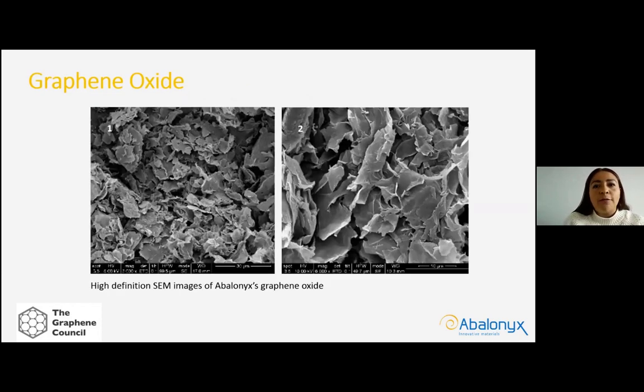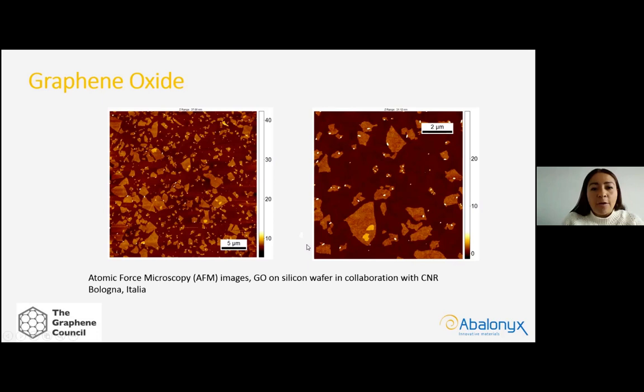So graphene oxide. Here I am showing you some SEM images of graphene oxide. These images are taken in bulk materials, so you cannot see here single sheets of graphene oxide, but you can see already the sharp edges of this material. And here is the AFM image of GO taken on silicon wafer, where you can see a single layer of graphene oxide. The average thickness of this material is 1 nanometer, and the flake size is between 1 and 2 micrometers.